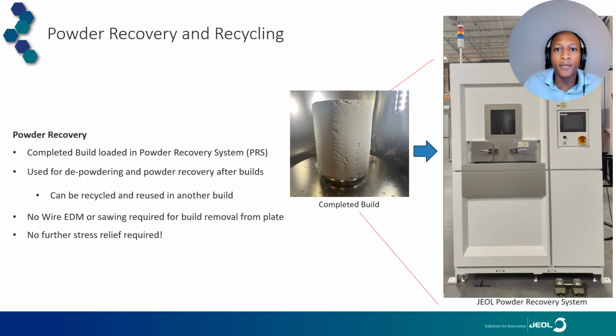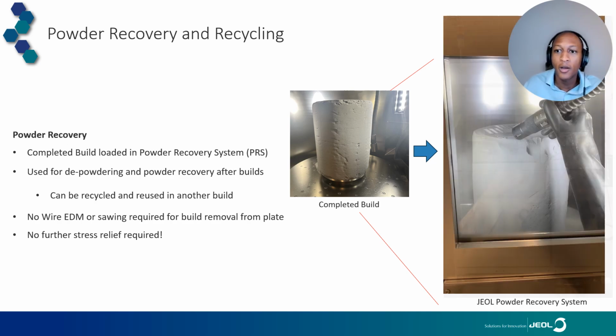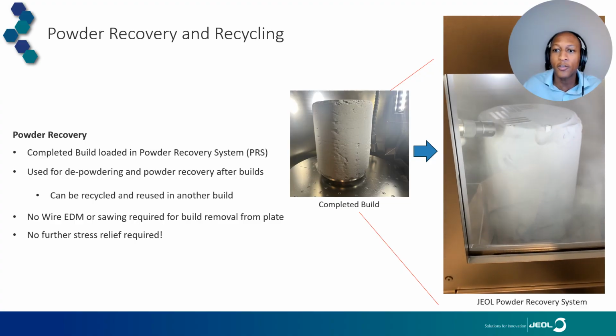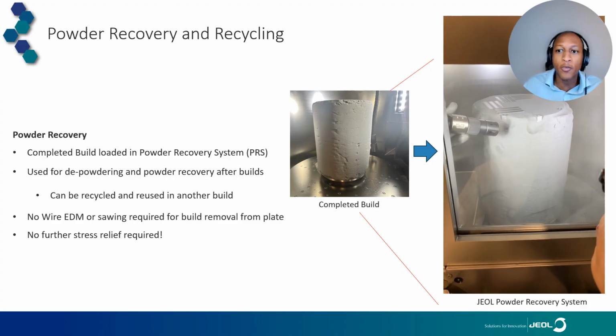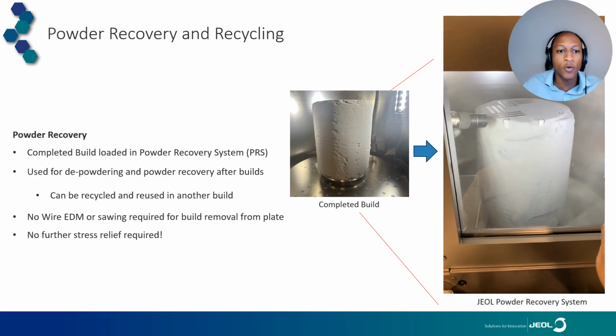After our build is completed from the JAM 5200, our parts are surrounded in sintered powder, and that powder must be removed from the parts. And we use a powder recovery system to remove all the sintered powder from our parts. The powder recovery system is a large blasting cabinet that we use with air in combination with a nitrogen environment to remove that sintered powder and blast those powder particles off of our part. So you'll see next is a video of us blasting and removing that sintered powder. And all that sintered powder can be removed and recycled and reused into another build.